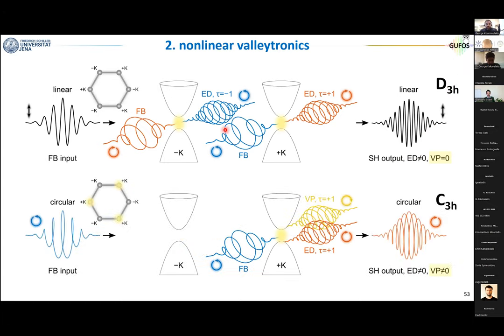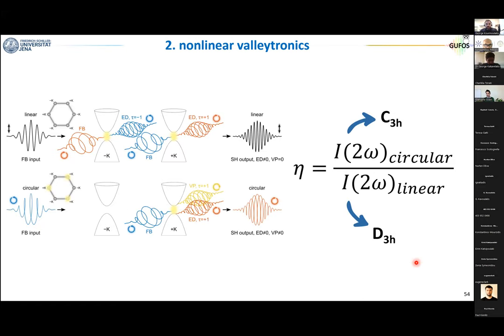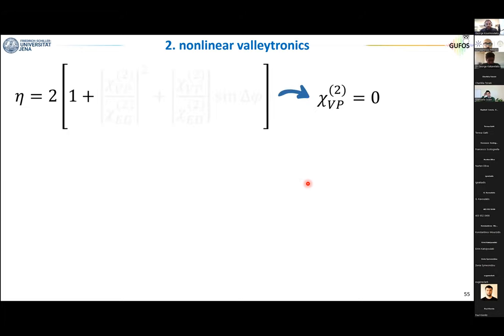If we now shine circularly polarized light, the point group changes because we are breaking time reversal symmetry. Our second harmonic comes not only from the electric dipole, but also from the valley polarization. Now, I want to convince you that if you take the ratio between the intensity when you shine circularly polarized light and the intensity when you shine linearly polarized light, this ratio contains information about the valley polarization and about the broken time reversal symmetry. Again, for this, we will need a bit of algebra, but I will skip it and go quite fast.